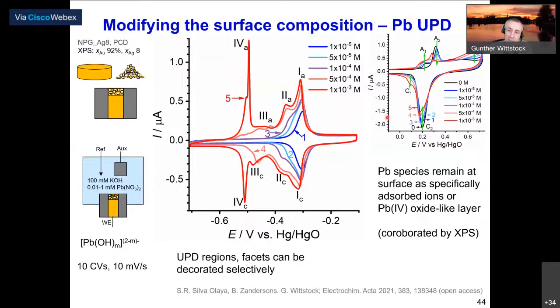On the other hand, the lead species also stay on the surface if we go to positive potential. So then they form plumbite species or even PbO2. And so we can cycle this again and again and get a stable coverage, which depends on the volume concentration of lead species. Now, this phenomenon can now be used to selectively take out certain sites of the nanoporous gold surface and then see which effect this has on electrocatalysis.